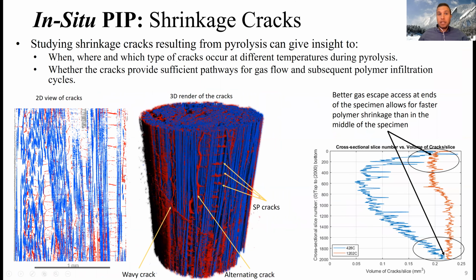Another thing to look at is shrinkage cracks. Shrinkage cracks resulting from pyrolysis can give insight into when, where, and which type of cracks occur at different temperatures during pyrolysis. Over here, you can see the 2D view of the cracks, and you can see that there are cracks that are horizontal. This is what Natalie calls the semi-circular cracks, and the cracks that are just connected and wavy. You can see it better after the 3D segmentation over here.